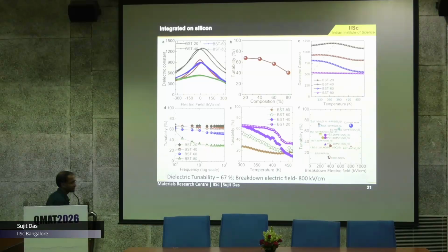Again the phase transition is pretty broad for these compositions when we measure the dielectric constant with temperature. Frequency stability is pretty good except for the BST80, and temperature stability is okay for the BST20 with respect to the other compositions. Now we compare our on-silicon data with the other literature. We found that in our case the tunability is pretty high, as well as the breakdown voltage.